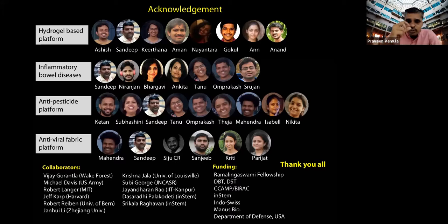By tuning the amount of intermolecular interactions, one can modulate the self-assembly process to make hydrogels, organogels and so on. And during this self-assembly process itself, if you incorporate the drug, they capture the drug and encapsulate it as they form the gels. Because once you form the gels, you can't put the drug in; it's like diffusion, a very inefficient process. It doesn't go. So that's why we tend to encapsulate while forming the gel itself. That's why we don't see much non-specific release. Otherwise, it can easily diffuse out without enzymes, right? So that's why self-assembly is very critical here, how you modulate that.